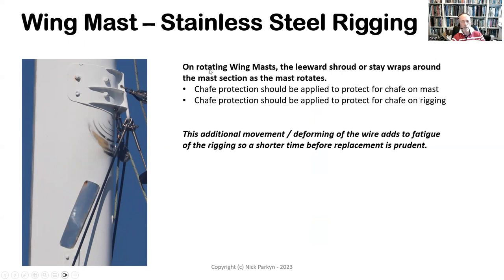One of those things is actually on rotating wing masts that we find, of course, on multi-hulls. And we can see here in the picture that there is some chafe protection being applied to the edge of the mast, because what happens is when the mast rotates, a wing mast is always rotated up to windward to give you a smooth entry onto the sail. And in doing so, the leeward shroud or stay, as the mast rotates, comes up against the mast surface and touches that.